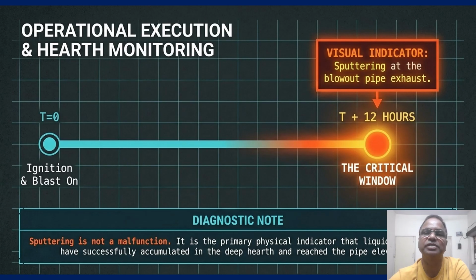The operational impact of missing this signal is severe. If you leave the pipe in too long after sputtering starts, it will melt our plug completely, making the subsequent taphole opening much more difficult. So once sputtering is confirmed, we begin the high-stakes tactical transition to the first cast.